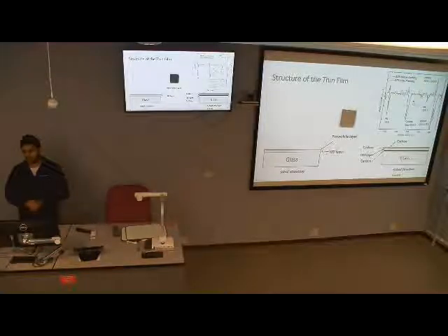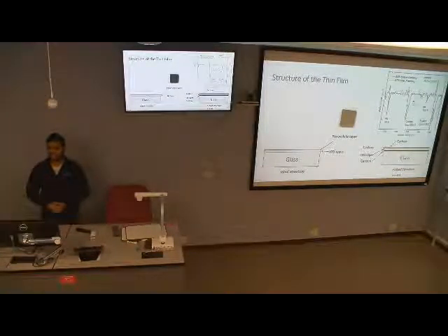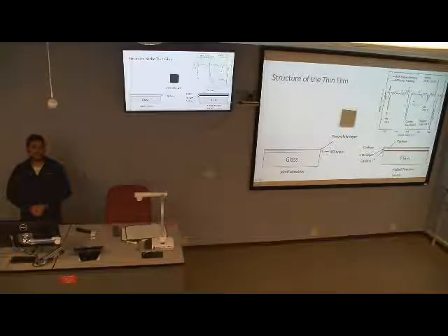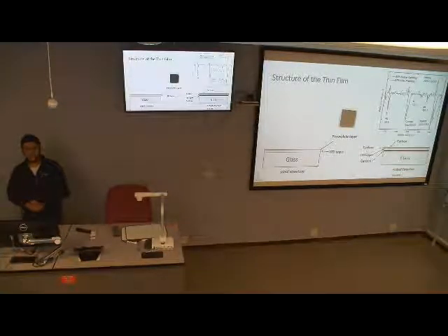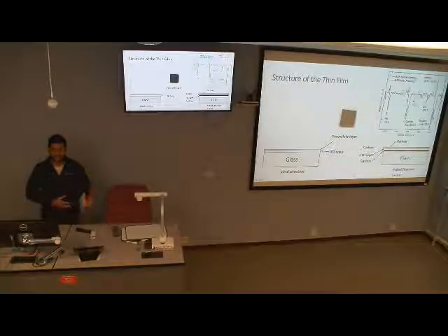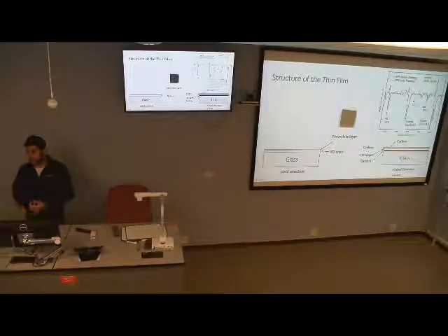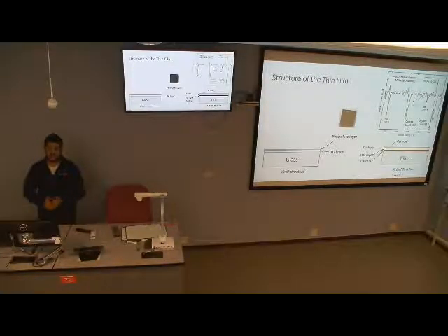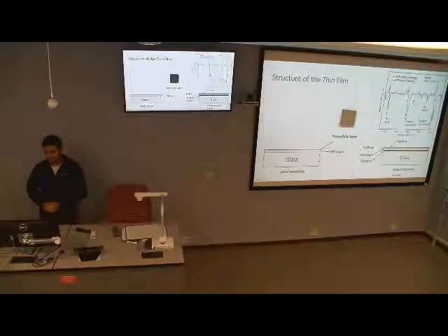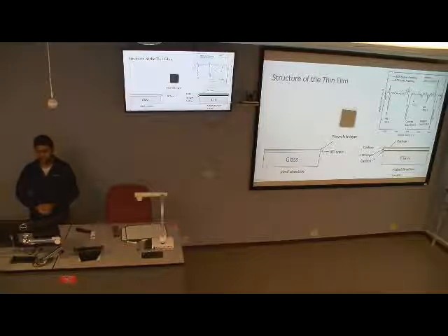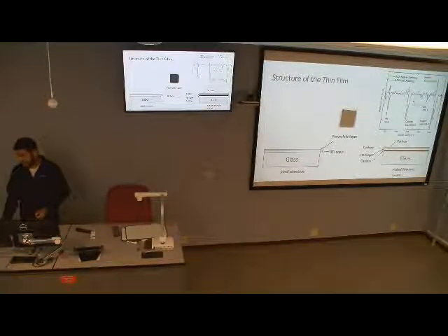So we have a lot of carbon dioxide and oxygen adsorbed on the surface initially, and we tried to remove those impurities by flashing at ultra high vacuum, and by sputtering with argon ions. But in both cases, if we flash the samples to higher temperatures, they tend to get destroyed. So we couldn't go beyond 400 Kelvin, even 380 Kelvin. It starts to deform the film, so we didn't want to dissociate those films.